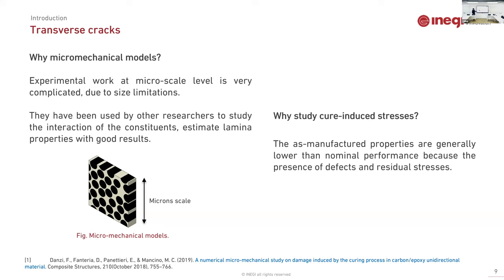Having this in mind, what happens if we also introduce the manufacturing process into this analysis? We can include how the manufacturing process could affect the material properties. This is relevant because the nominal properties of the material are usually different from the as-manufactured properties that we get in the composite, where we have a real part manufactured. Why? Because we have defects and we have residual stresses.